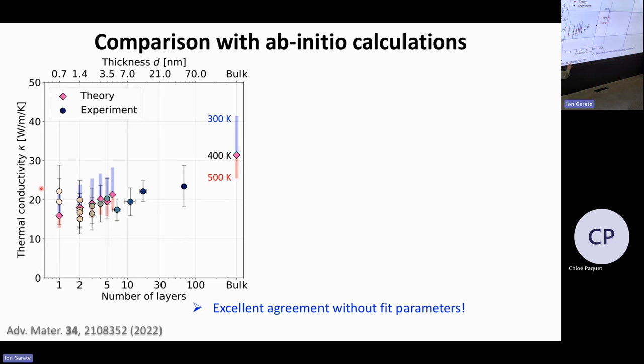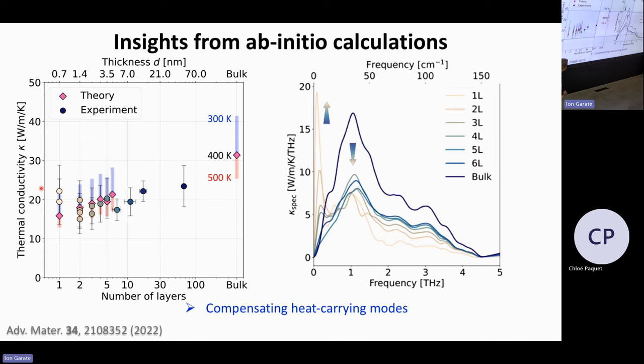So okay, we also did theory. These are ab initio calculations at room temperature and elevated temperatures, where you can calculate the thermal conductivity. I will not go into detail on that, but it actually matches extremely well. And one of the things that happens is that you get new phonon modes that are like flexural modes for the very thinnest films. So you get a drop in the normal modes that are carrying heat around 1 terahertz when you start thinning down. So that would normally lead to a lower thermal conductivity, but you have these new flexural modes for the thinnest films that actually carry quite a substantial amount of heat. And that compensates the fact that you have less heat carried around 1 terahertz. So that's why it's so flat.